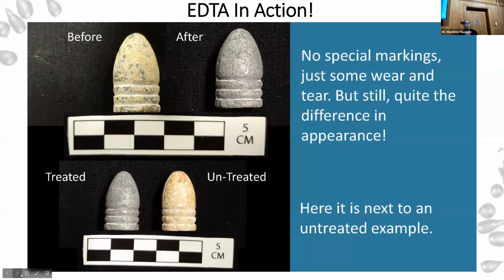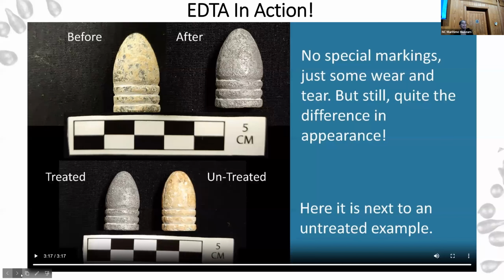Or you can do it as you saw, where I cheated. I used a hair dryer. If you need to dry something very quickly and thoroughly, which typically we try not to do, but for expediency's sake, that's what happened here. So you can see the before and after example. This is our bullet pretreatment, and you can see just how much material the EDTA was able to remove. And this is a comparison of our finished treated project with one of its untreated compatriots. You can see the differences in the surfaces. Unfortunately there aren't any particular markings that you can really see on the surface at this point, but if there were, they'd probably stand out a little bit more.